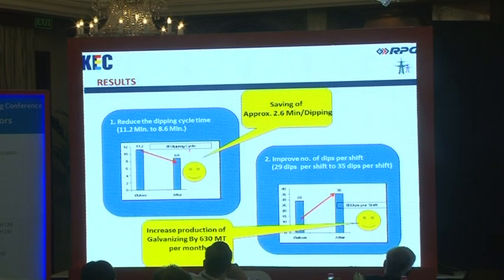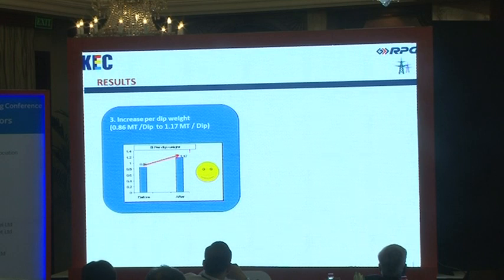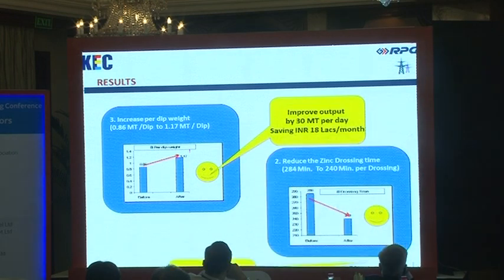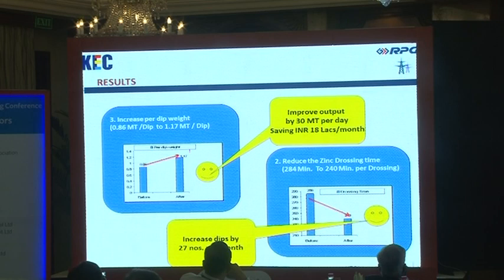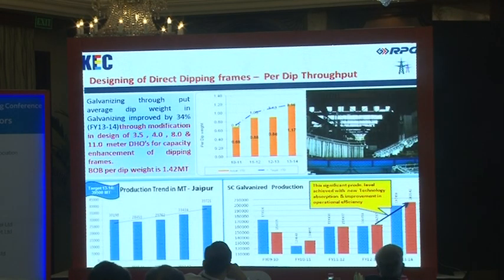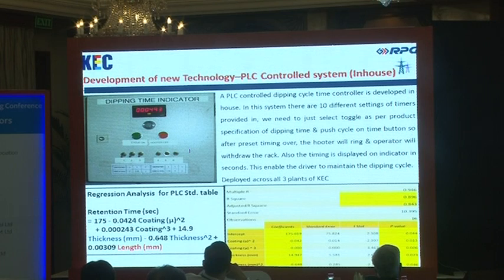By doing this, we have reduced our dipping cycle from 12 minutes to 9 minutes. So our number of dips improved from 29 dips per shift to 35 dips per shift. An average of 600 metric ton production per month has been increased in the plant. The per dip weight in a single carrying is increased from 0.86 to 1.17 metric ton. Again, 30 metric ton per day has been increased for that.